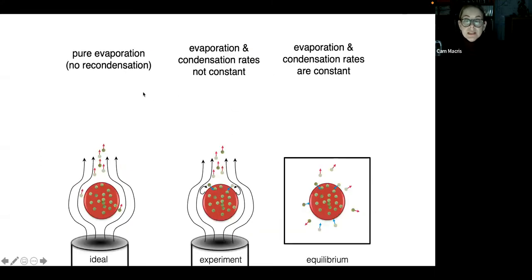So here, I'm showing you a spectrum of evaporation behaviors. So on one end, this end over here, you've got what we call ideal or free evaporation. This is where all evaporated particles are quantitatively removed from the melt such that no recondensation is occurring. So this would be the case for evaporation in a vacuum. And if this was happening in our experiments, it might look like this cartoon that I have created here, where all of the evaporated particles are immediately carried away in the gas flow and none of them recondense.